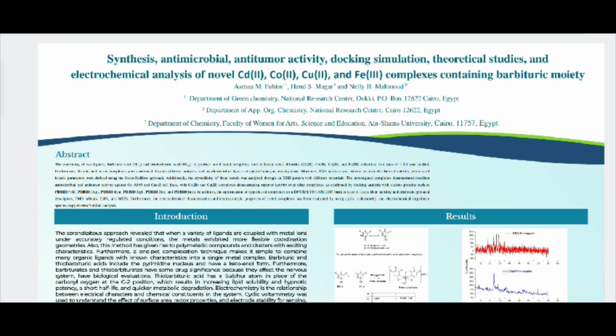In addition, the optimization of ligand and complexes on a DFT B3LYP LANL2DZ basis is used to assess their stability and determine physical descriptors, FMO orbitals, ESP and MEP. Furthermore, the electrochemical characterization and the electrocatalytic properties of metal complexes have been evaluated using cyclic voltammetry and electrochemical impedance. The serendipitous approach revealed that when a variety of ligands are coupled with metal ions under accurately regulated conditions, the metal exhibited more flexible coordination geometries.